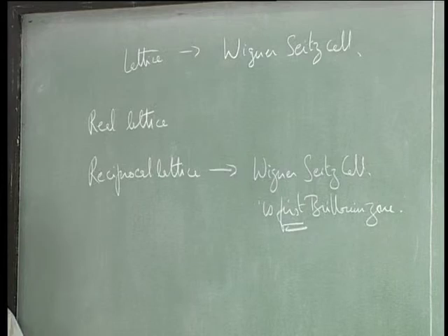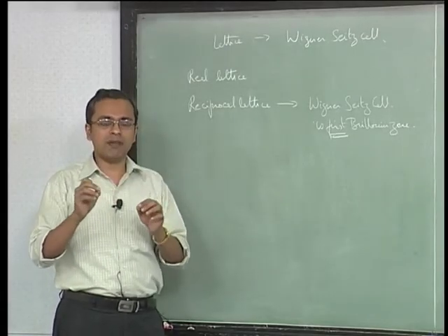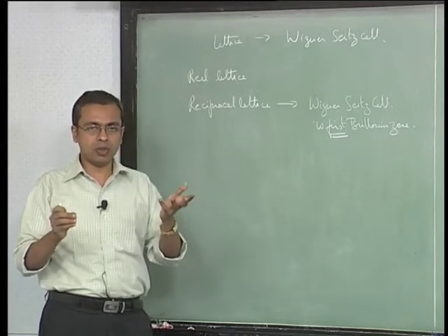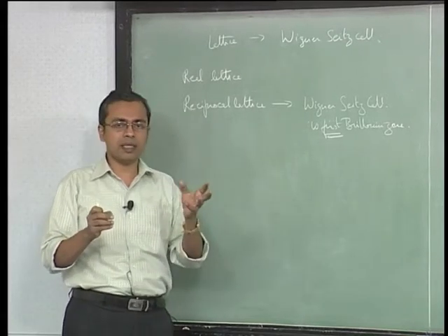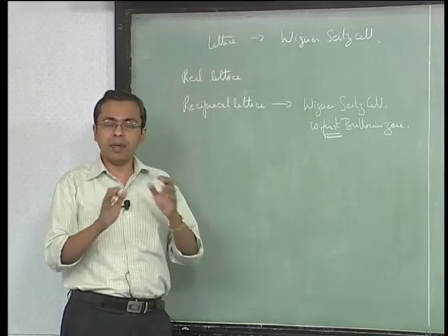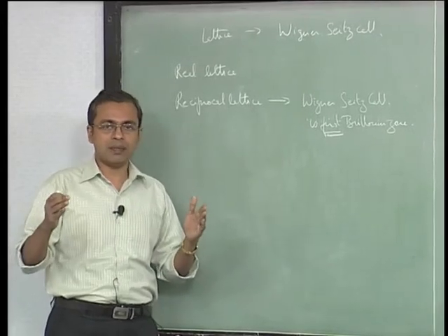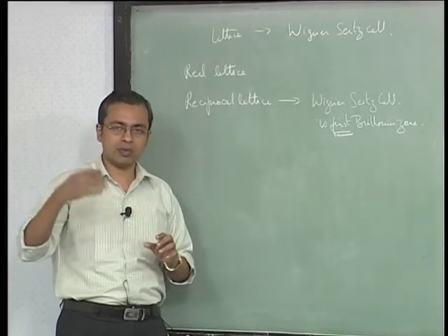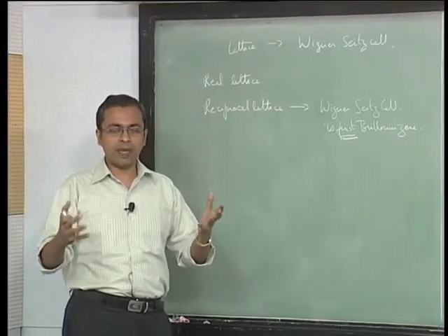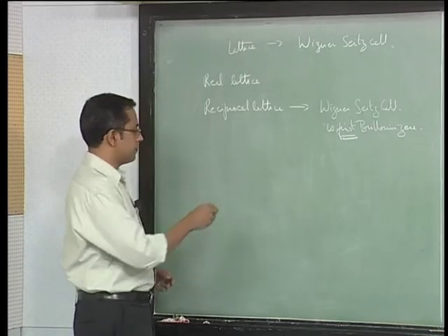Instead of talking of lines we have planes, and all those planes intersect along lines, and so the shapes that we identify begin to look complicated. Okay. So I have been able to show you the first Brillouin zone rather clearly. If you look at the second and third Brillouin zones in 3D, it looks rather complicated, but the process is exactly the same. You simply keep identifying planes that bisect the reciprocal lattice vectors to neighbors that are further and further away, and then you keep identifying the structures where you cross only one Bragg plane and no further Bragg planes.